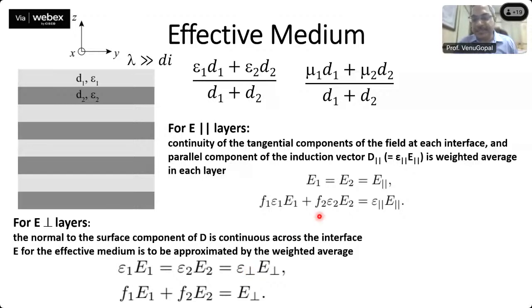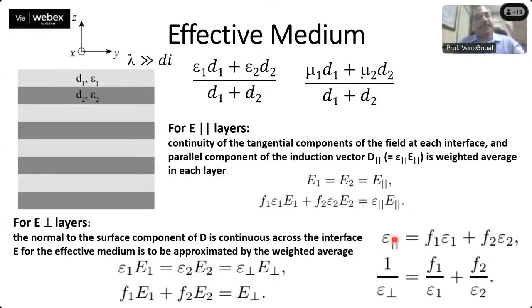So from these, what we can get is, for a layered structure like this, a simple layered structure, which is an effective medium, we can now generate materials which have different types of response in different directions. Right? So the E parallel and E perpendicular expressions are given here. Depending on what the epsilon 1 and epsilon 2 are, now we can design materials which can act, for example, epsilon 1 is negative, that is a metal,